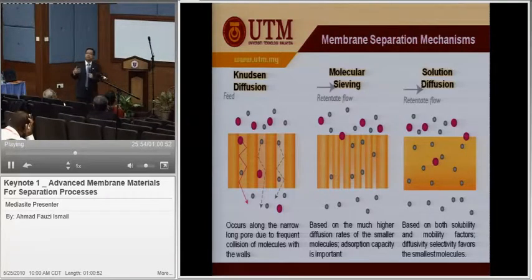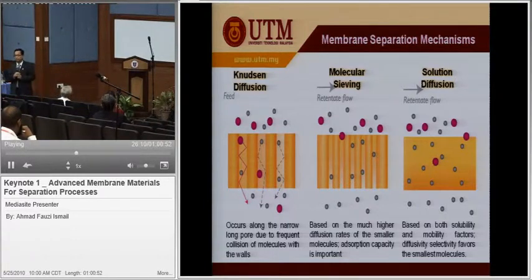And of course, there are a few separation mechanisms involved in this technology. Some call it Knudsen diffusion, some call it molecular sieving, some call it solution diffusion. For Knudsen diffusion, the separation occurs along narrow, long pores due to frequent collision of molecules with the wall. Whereas molecular sieving is based on the much higher diffusion rate of the smaller molecule, and adsorption capacity is important in this case. Solution diffusion is based on solubility and diffusivity.